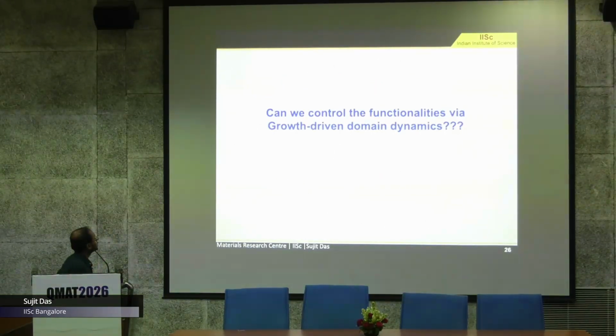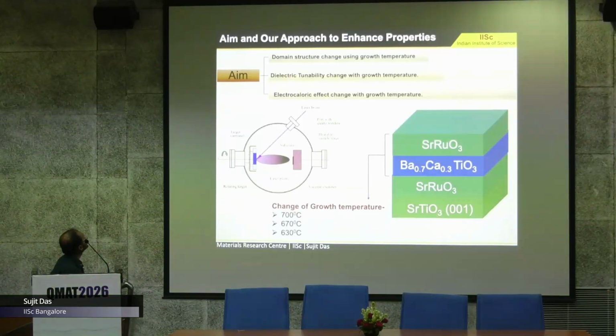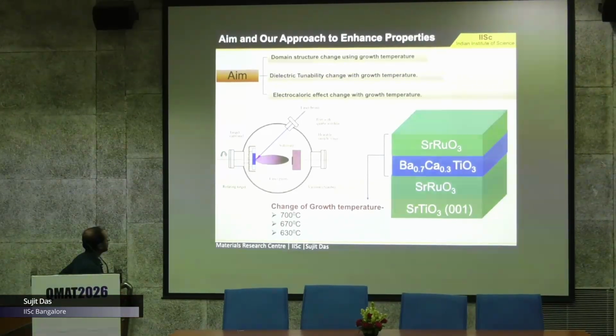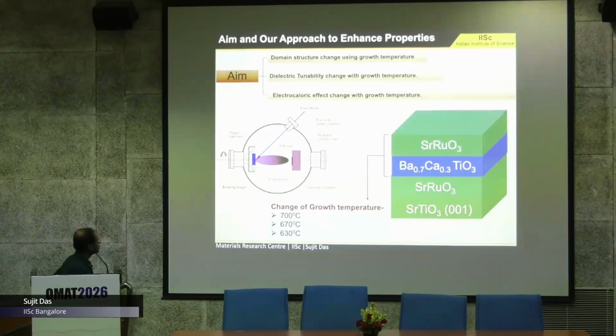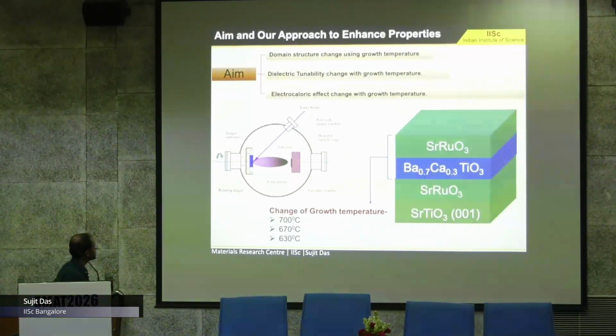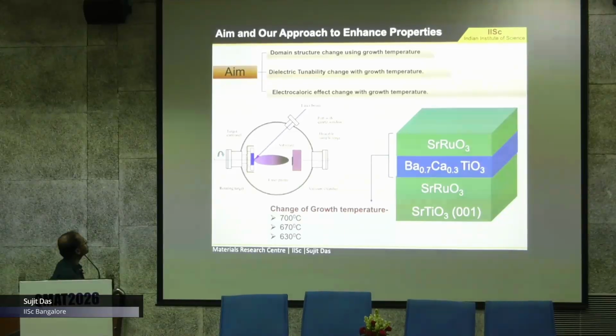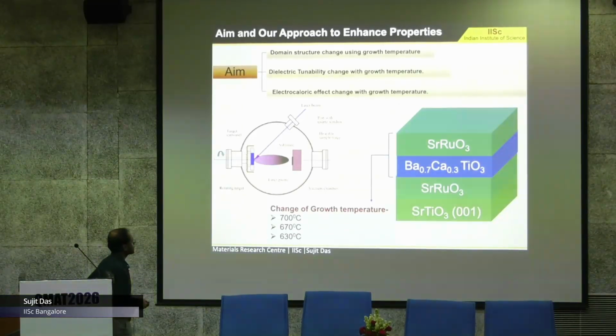Now, can we control the functionalities via growth-driven domain dynamics? What we have done is take this particular composition, calcium-doped barium titanate. We also checked a similar study on strontium-doped barium titanate, but here I am showing only the calcium-doped barium titanate. We check the domain structure change with growth temperature, the dielectric tunability also changes with growth temperature, and we have also seen another application, the electrocaloric effect, with growth temperature.